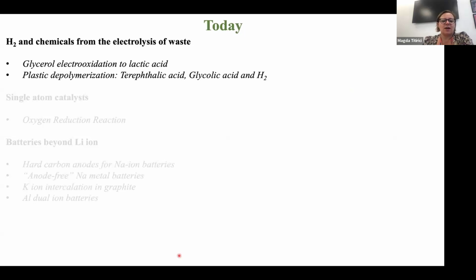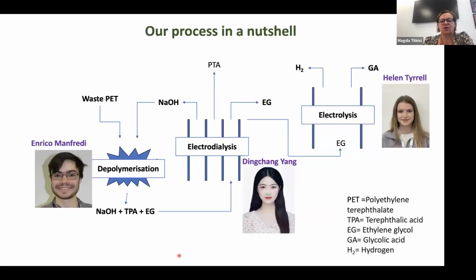Inspired by this, we then looked at plastic depolymerization as well to make terephthalic acid, glycolic acid, and hydrogen. So our process in a nutshell is the following. We're taking waste PET. We are doing a depolymerization process whereby we add some solid sodium hydroxide flakes to it, and we shake it a little bit with mechanochemistry. What we get out of this is terephthalic acid, which is the monomer of PET, ethylene glycol, and sodium hydroxide. Then we separate this using electrodialysis back to sodium hydroxide, which we use back in our depolymerization, terephthalic acid, and ethylene glycol.